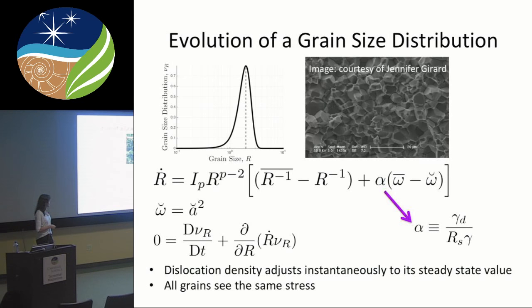An important assumption is that I eliminated the dislocation density time scale. I'm saying that when the grain size is changing, my dislocation density adjusts immediately to its steady state value. This is just saying that dislocation kinetics are infinitely fast. Secondly, I said that the stress seen by all of these grains is the same. So what this means is that in the model with an ensemble of grains, contrary to just two grains, I will not be able, at the moment, to explore this oscillating behavior. But I can still test some of the predictions from the two-grain model, as I'll explain in a second.